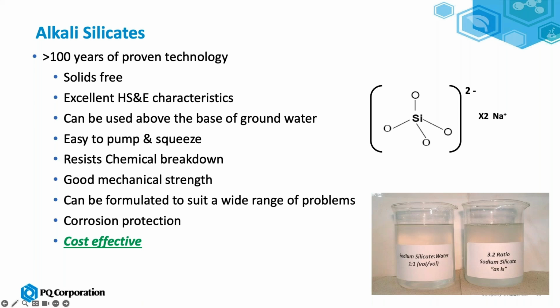As far as the tool and toolbox goes, very, very old technology. The first patent on the use of silicates is back in 1922. We're seeing a bit of a resurgence towards silicate-based technology, and there's a lot of reasons for that. It's a solids-free technology. If you look over on the right, that's the silicate molecule in its simplest form. So we've taken silica, reacted it with an alkali, soda ash, and then dissolved it. So that would be the monomer, and we also would have in solution dimers, trimers, oligomers of that silica monomer. As you can imagine, a product based on sand and soda ash has excellent HS&E characteristics, so it is allowed to be used above the base of groundwater.